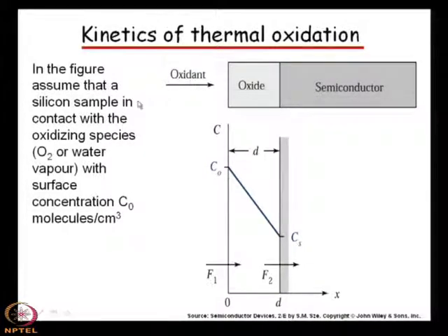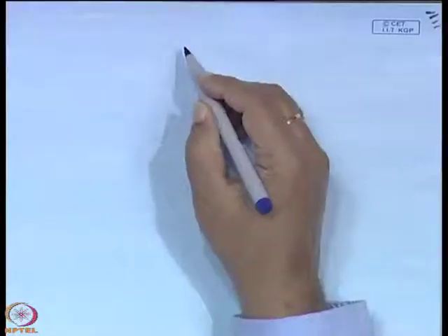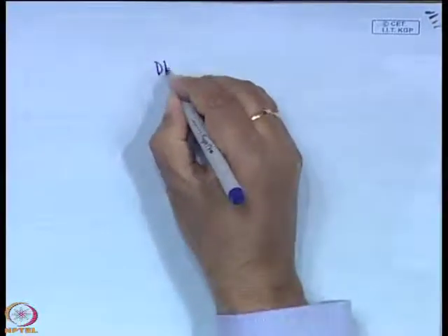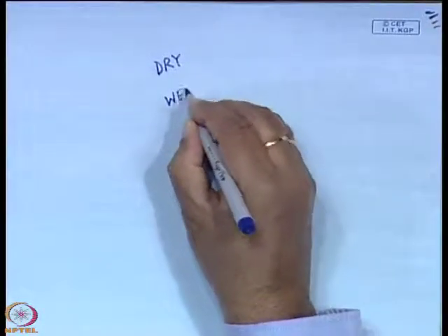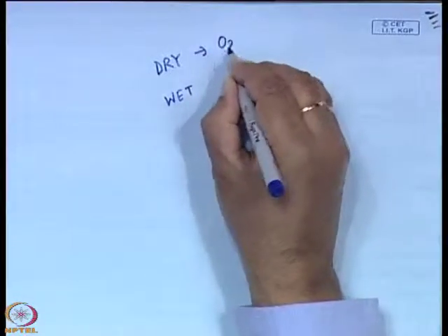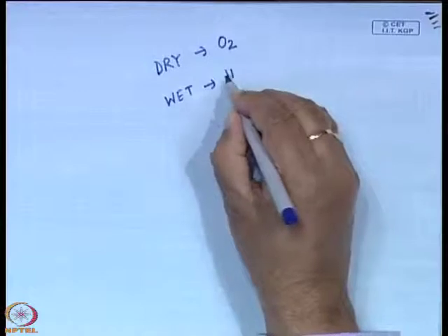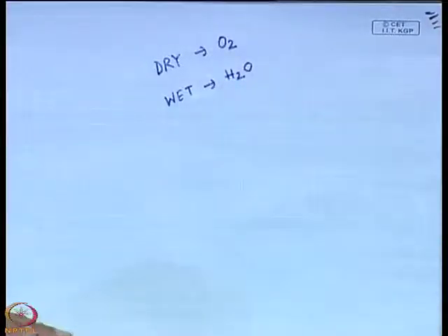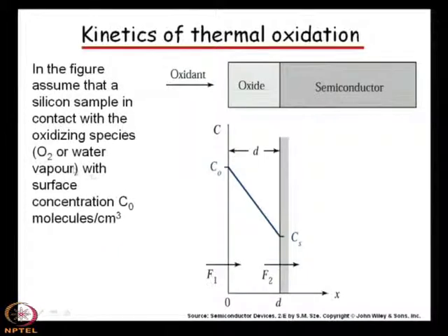That means, we have assumed a silicon sample in contact with the oxidizing species. The oxidizing species can be oxygen or water vapor, because we have discussed earlier that the oxidation can be done by two processes. One is the dry oxidation, another is the wet oxidation. In dry oxidation generally oxygen is used, and in wet oxidation water vapor or steam is used. So, in the view graph, the oxidizing species could be oxygen or water vapor depending on whether the oxidation is dry or wet, with surface concentration C0 molecules per centimeter cube.